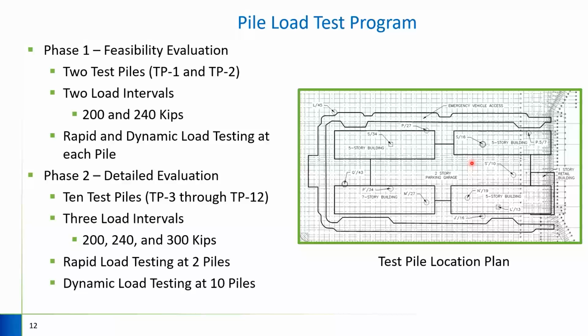And with this, we determined that we would use rapid and dynamic pile load testing at each individual pile location. And the purpose for this was that should we end up needing to use the dynamic load testing, that we could correlate the test results between the rapid and the dynamic load test to hopefully get a factor of safety of 2 should we need that additional capacity out of the ultimate loads. Once this was complete, obviously, since we're presenting on this topic, we ended up having a successful phase 1.